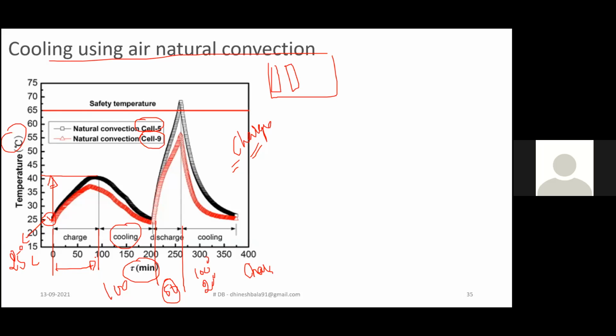So in this particular study, what I try to do is charge the battery and keep it idle for another 100 minutes, and then I try to discharge the battery. At the time of discharge, when I'm monitoring the cell temperature, the temperature has risen above 65 degrees Celsius. For this particular case, the safety limit is noted as 65 degrees Celsius. In cell number 5, the temperature has risen above 65 degrees Celsius.